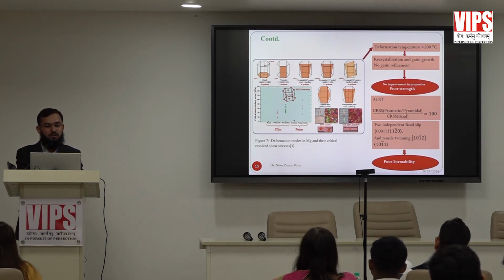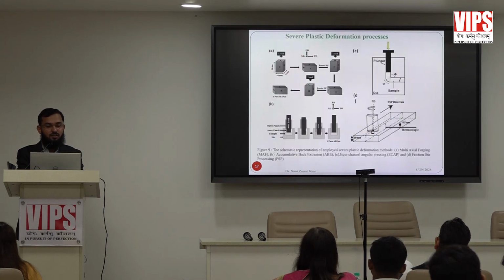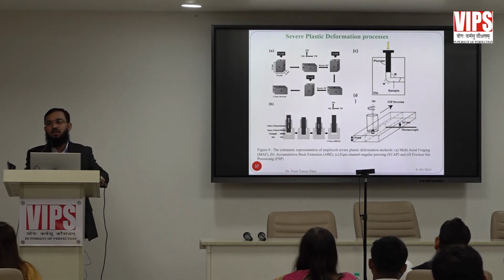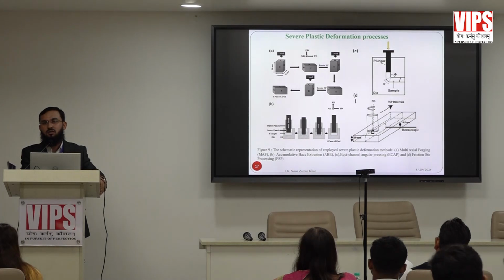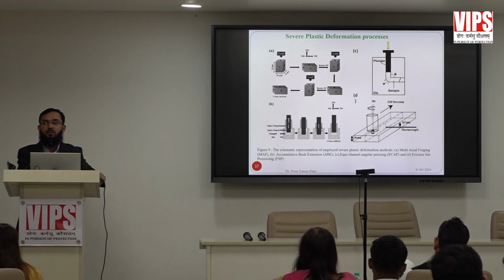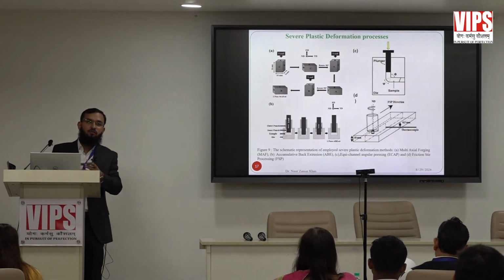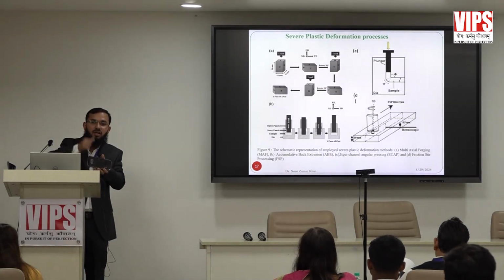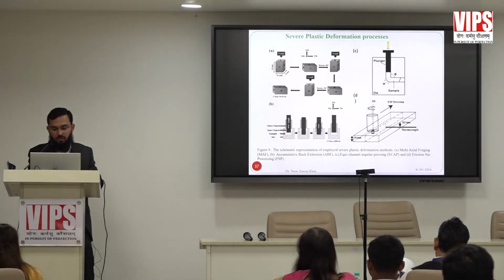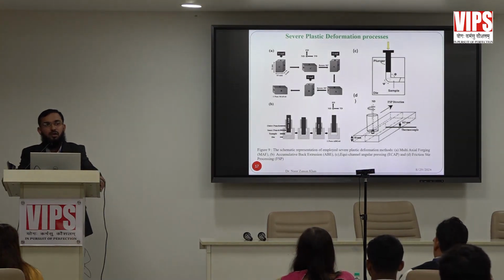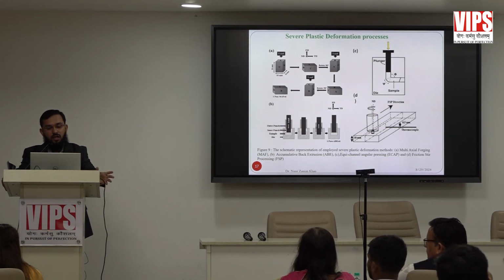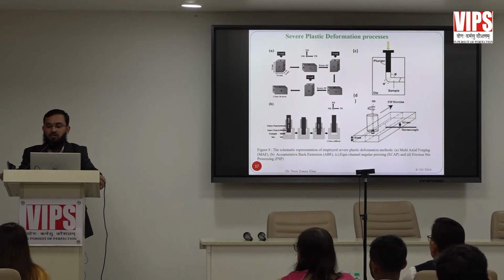So what could be the possible solution? Again, texture. We can improve the strength and we can minimize the texture. We can enhance the texture weakening. The possible solutions are severe plastic deformation processes. Either you go for multi-axial forging, hammering in this direction and this direction. If you are performing forging operation in multiple axes, you can achieve severe plastic deformation. Another could be accumulative back extrusion, equal channel angular pressing, and the last is friction stir processing. And my area is friction stir processing.